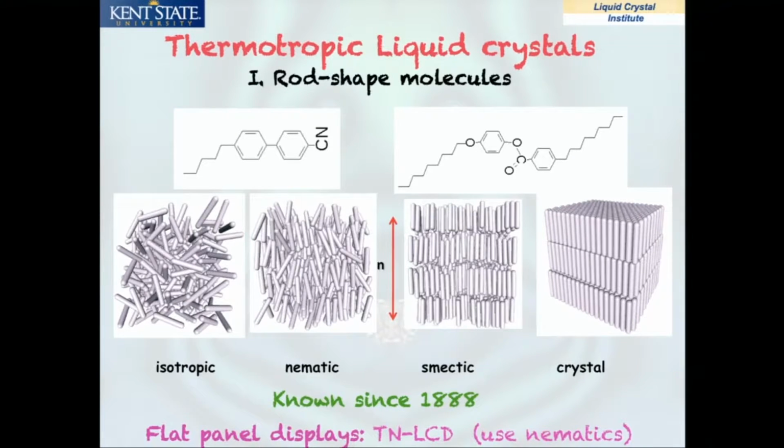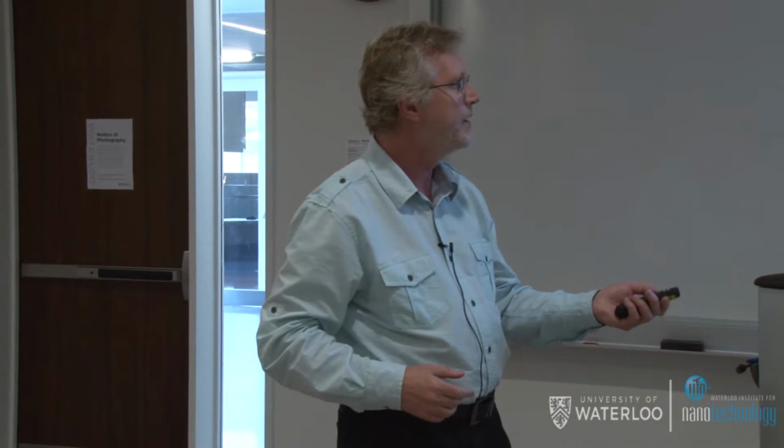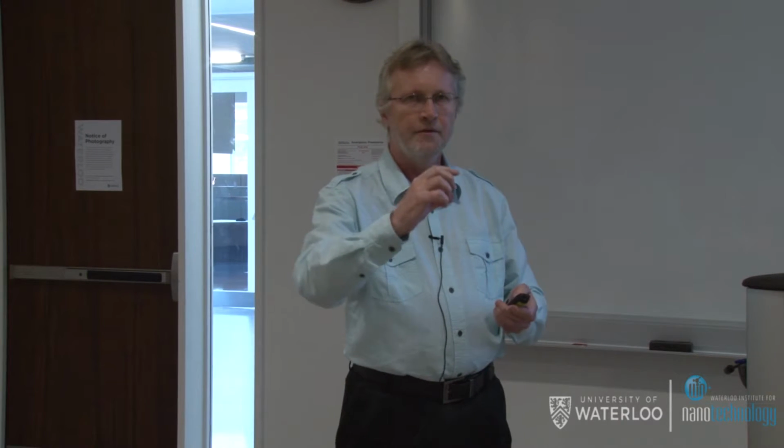In some materials, which are the smectics, they are two-dimensional fluids. The centers of mass are random only in two dimensions. In the third dimension, they make a periodic structure. So this is the first nanostructure, because you have a nanoscale periodicity of a few nanometers. A typical molecule which would make that phase is shown here. You have two benzene rings, which is considered a rigid core, and some aliphatic tail, which is flexible. And this is really important to make the layering, because there is nano-segregation.